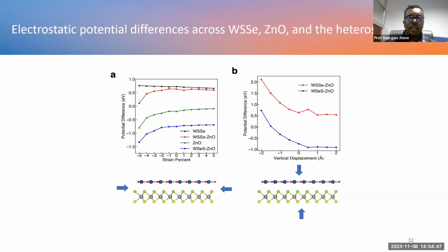And why zinc oxide? When we combine it with zinc oxide, the lattice mismatch is less than 5%. That means this material can be experimentally fabricated. So that is the reason. We start from Janus and then go to zinc oxide because of the lattice mismatch.